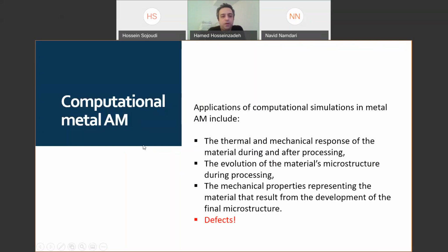So what do we want from computational metal additive manufacturing? We want to simulate the thermal and mechanical response of the material during and after processing, the evolution of the material's microstructure during the processing, and the mechanical properties resulting from the development of the final microstructure. So we want to simulate thermal history and mechanical response such as residual stress and deformation. We want to simulate the final microstructure, and we want to see the mechanical properties of the printed sample, the local mechanical properties.